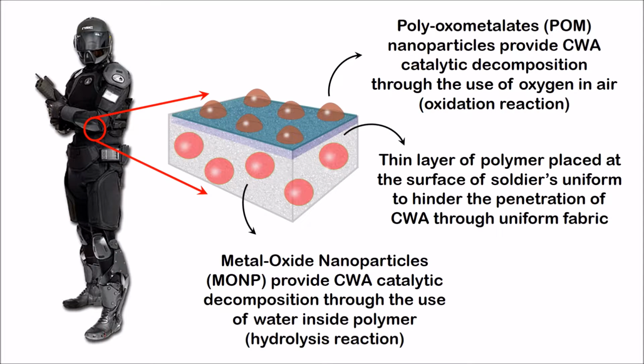We would have a two-layer membrane in which at the surface of the outer layer we incorporate a class of active nanoparticles called polyoxometalates, or POMs. They are capable of decomposing agents by using oxygen available in air to provide an oxidation reaction.